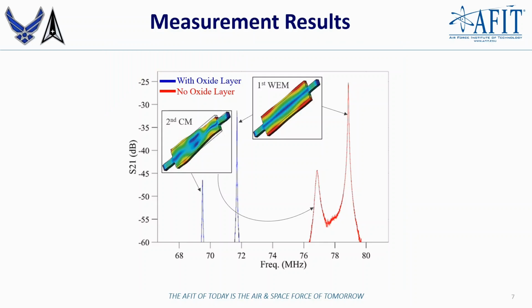So these are the measurement results from the 2-port S parameter characterization of our fabricated resonators. The blue curve represents the resonator with the oxide layer, and the red curve shows the resonator without it. Since both resonators have the same lateral dimension, the addition of the oxide layer shifts the frequency down. This is because the effective acoustic velocity is lower due to the oxide layer, which reduces the resonant frequency for both the second contour mode as well as the width extensional mode, the fundamental mode.